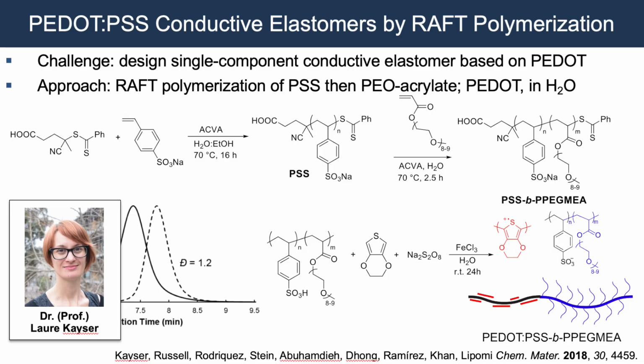Those are all static materials, but my group is interested in stimulus-responsive polymers, stimulus-responsive materials in general. There's a material that's used all the time for neural activation called PEDOT:PSS, which is a conductive polymer that contains a conductive region of PEDOT plus a polyanion called polystyrene sulfonate. The problem with this material, just the red part and the black part mixed together, is that those materials tend to be brittle and not very conductive unless you dope them, and they are subject to batch-to-batch variability.